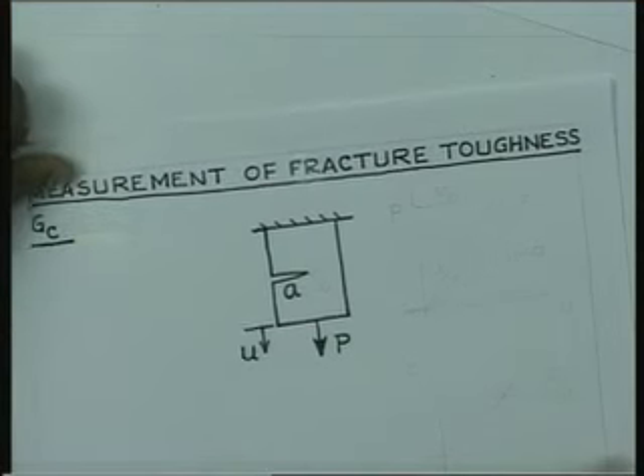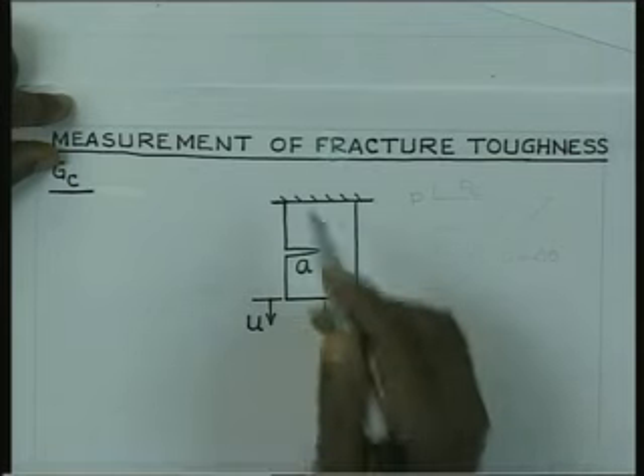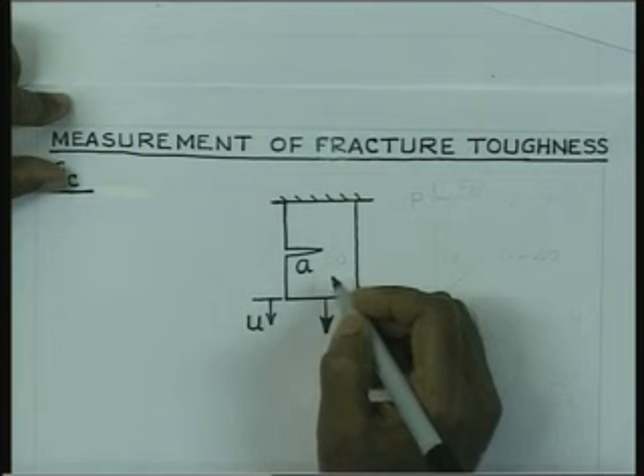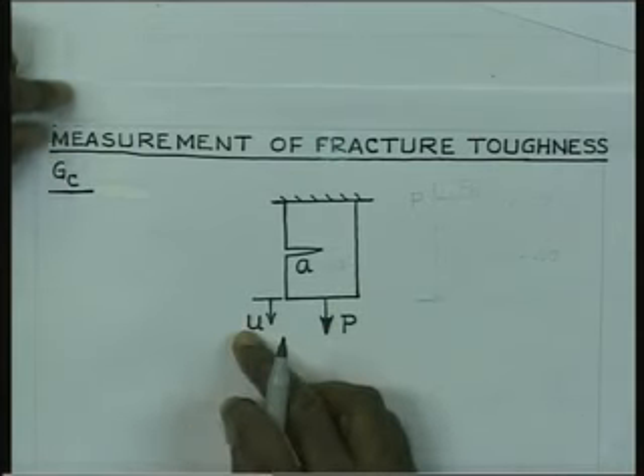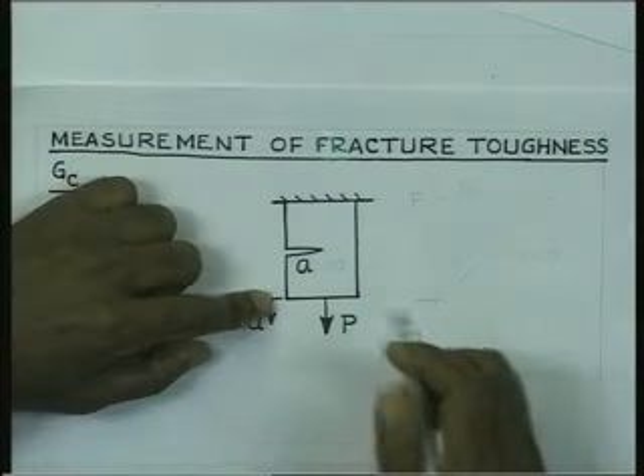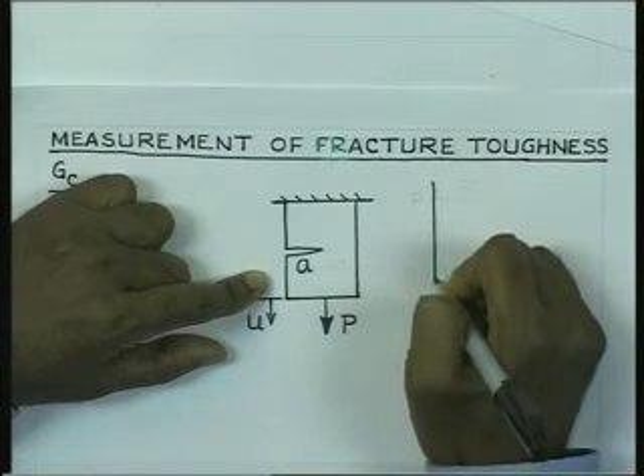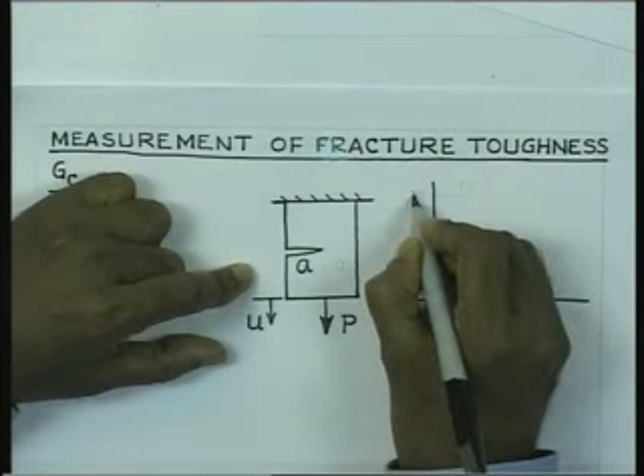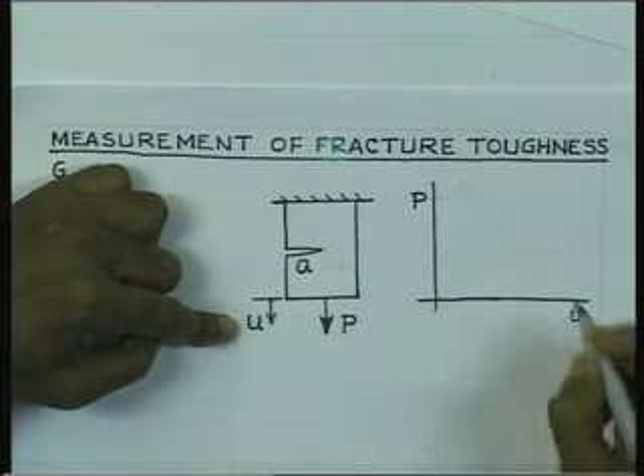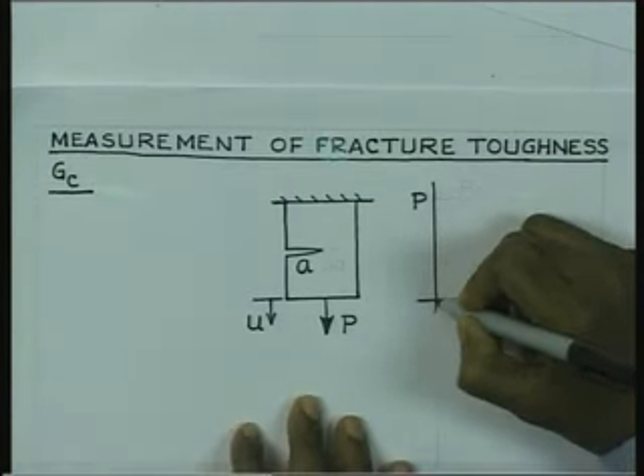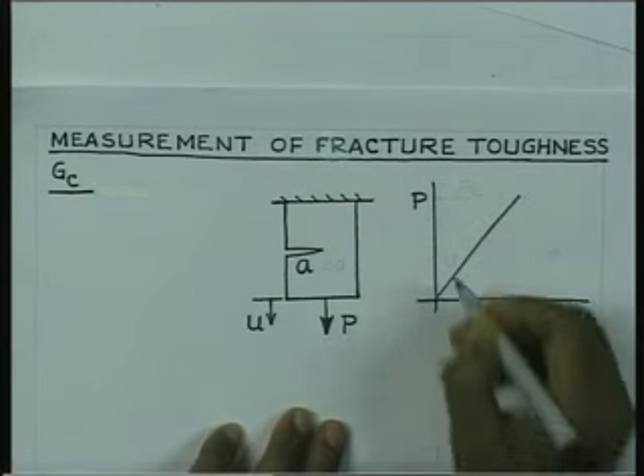One question which can come up: how do we go about determining this fracture resistance of the material? So, let us try to consider how we get the fracture toughness of the material evaluated experimentally. For that, we consider a specimen of this type and we apply the load here and try to monitor the displacement. If we consider a particular crack size a and plot the variation of the load with the displacement u, then since it is an elastic material, there is no plastic deformation or nonlinear deformation, so we are going to get the variation of load with deflection to be given by this.